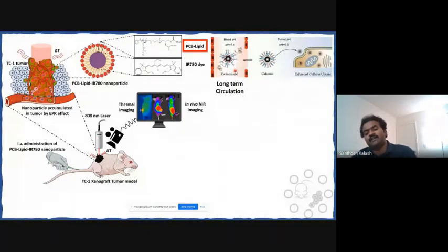One interesting fact about these zwitterionic polymers is that when they enter the tumor pH, which is less than 6.5, they become highly positive. Their surface charge turns from zero to a positive charge of more than plus 20. Due to this positive charge, they can easily bind to the cell surface, and they get taken up more by the tumor cells specifically.